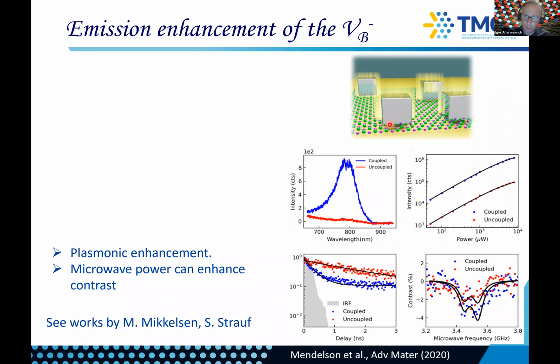And so you can, again, make an hBN, few layers, and put it on a gold and disperse cubes on top, and then achieve a very strong enhancement here within the nanoscale gap. And we've done it. And so here you can see that the coupled emission is enhanced by quite a bit. You can barely see the pristine VB.